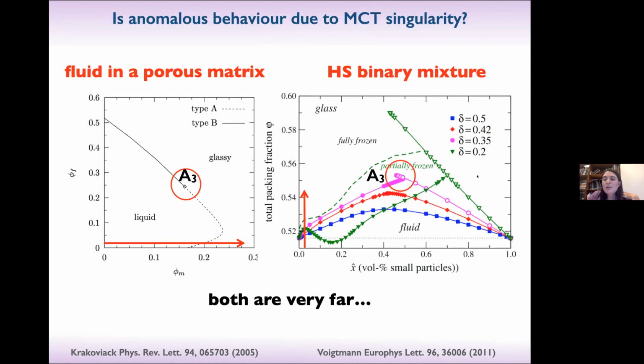If you focus on the hard-sphere binary mixture, I showed you before the phase diagram that Thomas Voigtmann had calculated, and the A3 singularity is here, but our simulation and experiment are here, at very low volume fraction of the small particles. So if we increase the packing fraction of the glassy matrix, basically we are far away from the higher order singularity. So it seems that we cannot recover this behavior from MCT here.